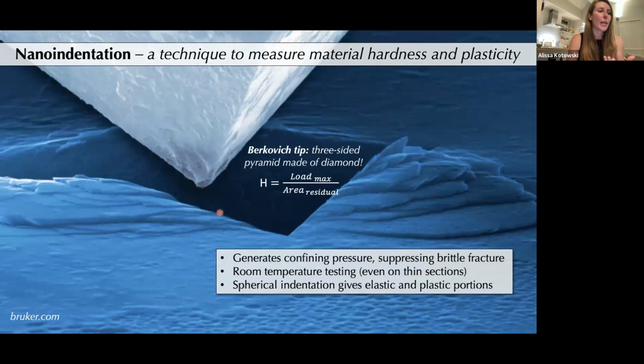And what you do is you take this, you press it into the surface of your material of interest. In this case, it's being pressed into a metal. The maximum applied load and the residual area from the indent are known and measured respectively. And if you take the ratio, then you can calculate the material hardness. So the tip also generates an in situ confining pressure. This suppresses brittle deformation in favor of material plasticity instead of brittle deformation.